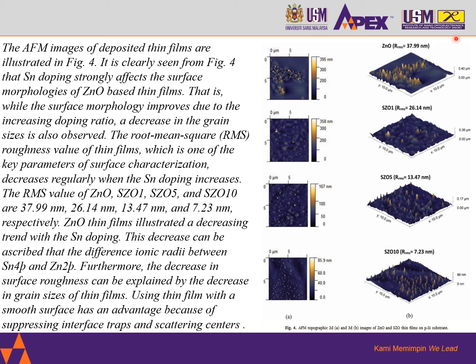That is, while the surface morphology improves due to the increasing doping ratio, a decrease in the grain size is also observed. The root mean square (RMS) roughness value of thin films, which is one of the key parameters of surface characterization, decreases regularly when the tin doping increases. The RMS values of zinc oxide, SZO1, SZO5, and SZO10 are 37.99 nanometers, 26.14 nanometers, 13.47 nanometers, and 7.23 nanometers respectively. Zinc oxide thin films illustrated a decreasing trend with the tin doping.